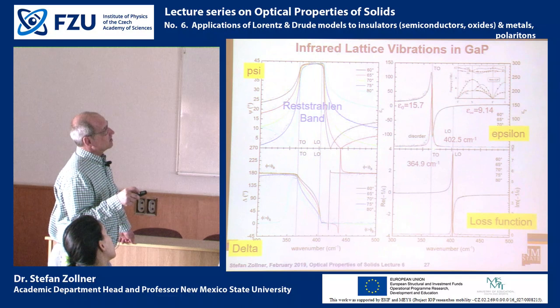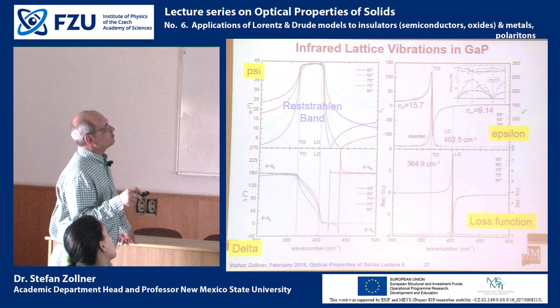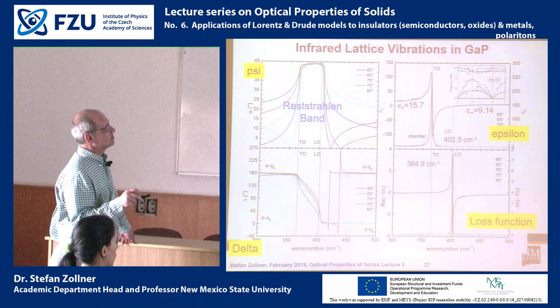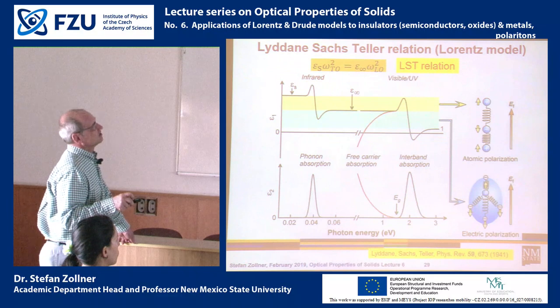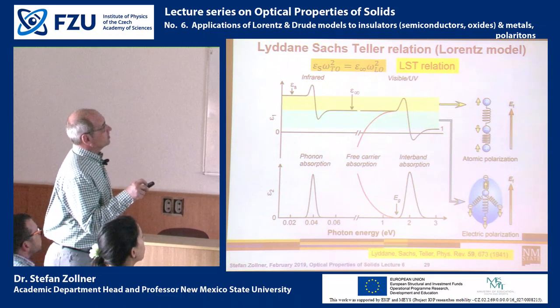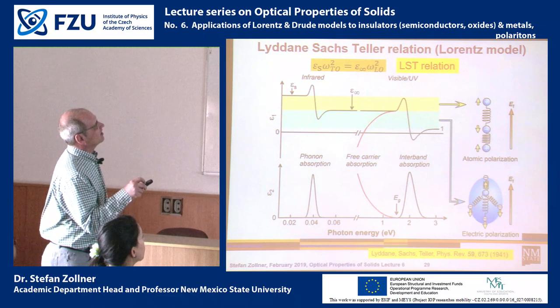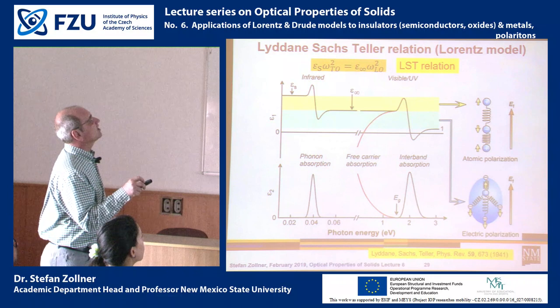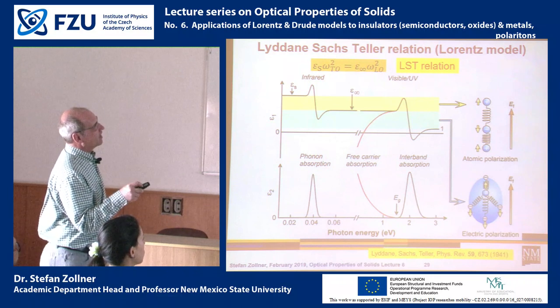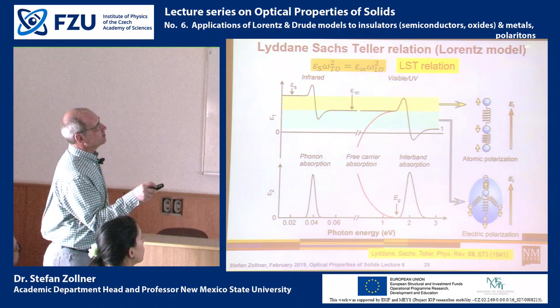We've seen here that from a fit to the ellipsometric spectra in the infrared for gallium phosphide, we can determine the TO and LO frequencies, and also the low frequency and the high frequency dielectric constant. So these are four numbers: TO and LO frequency, and static and high frequency dielectric constant. These four numbers are related through the Lorentz model, and determined by a fit to the Lorentz model.